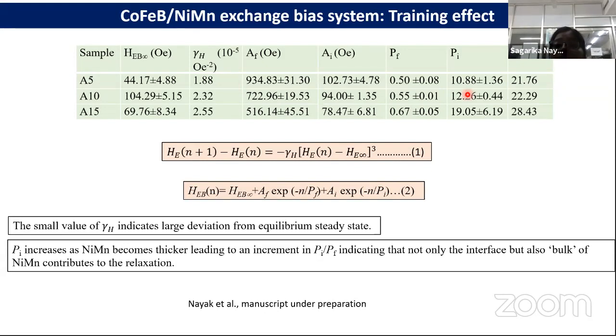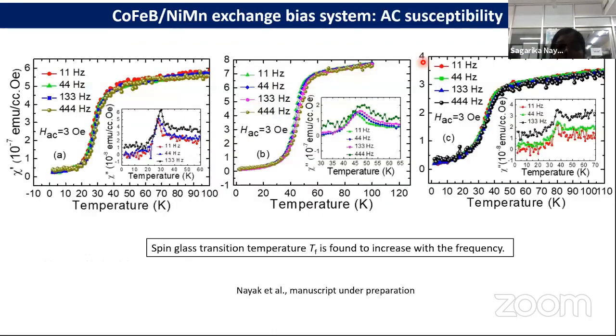And also we found that this ratio of pi by pf, which is the relaxation rate of rotatable and frozen spins, increases with increase in thickness of the nickel manganese from 5 to 15 nanometer, indicating that not only the interface but also the bulk spins of nickel manganese contribute to the relaxation mechanism.